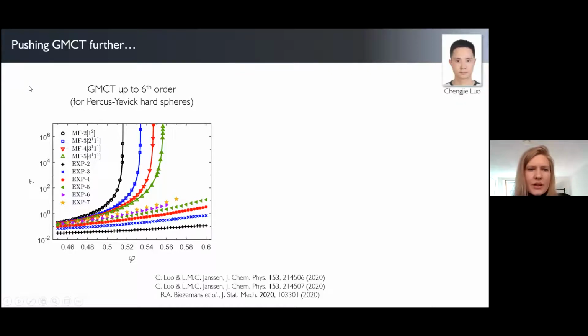So by now my group, this is work by my PhD student Chengjie Luo, has really pushed this idea to another 2 levels higher in the hierarchy by just improving the numerical algorithms. So these are results for hard spheres where you see the relaxation time here as a function of the packing fraction. And interestingly, what we find is that all these mean field closures always give us a power law divergence of the relaxation time, while these alternative closures that we call the exponential closures actually never give us a sharp glass transition, and also don't really show power law growth, but rather more exponential or activated dynamics.